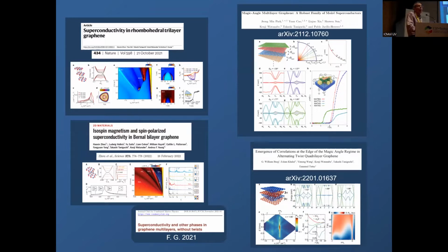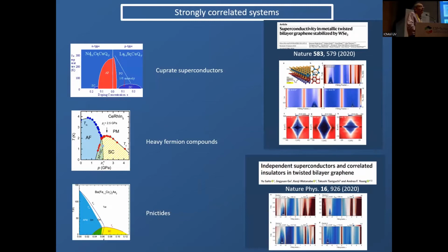You have to go to like 50 millikelvin or so. I mean, the critical temperatures are in between 50 and 100 millikelvin, but nobody expected superconductivity in pure, perfect graphene samples, without twist or anything, and it turns out that there is superconductivity there, even if you have to go to very low temperatures. And one of the reasons this topic is interesting is because the phase diagram shown by these